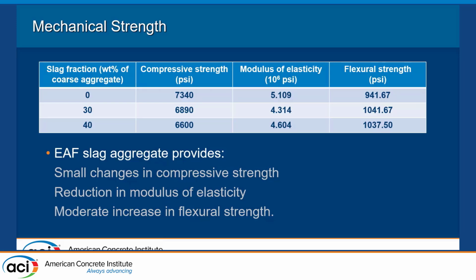And from this testing, we wondered if this decrease in modulus of elasticity may cause a decrease in flexural strength, which of course would mean that the material does not have any positive impacts on concrete. So we performed flexural strength tests. We did simple beam tests with center loading to test our flexural strength, and we actually found that there is a moderate increase in flexural strength in the beams using EAF slag aggregate, which was a very interesting development.